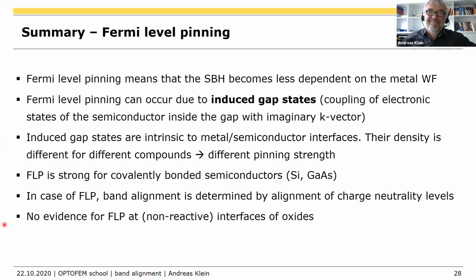For the intrinsic interface states, it depends on the surface orientation. It depends on the surface preparation. You can get this even for epitaxial interfaces. There is one very famous example for interfaces between silicon and nickel silicide, which are nicely epitaxial, which you can prepare with different surface orientations. And surprisingly, people find that the Schottky barrier height for the different orientations and different surface terminations, you can grow in principle the nickel silicide with 2 orientations on the same silicon surface, you get quite substantially different barrier heights.